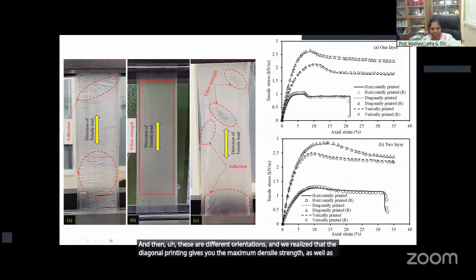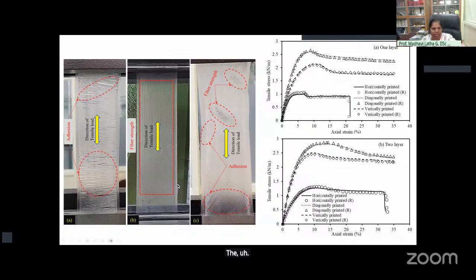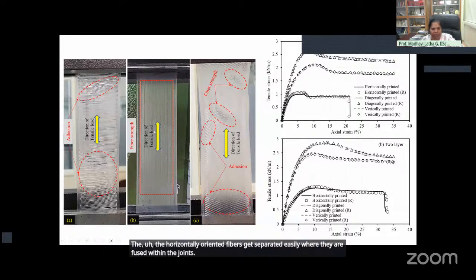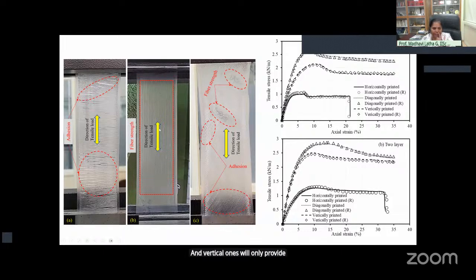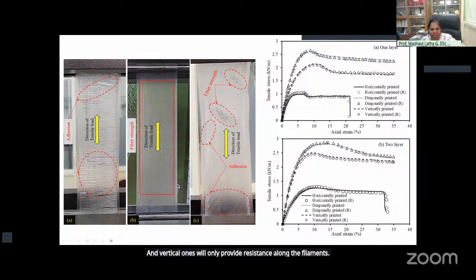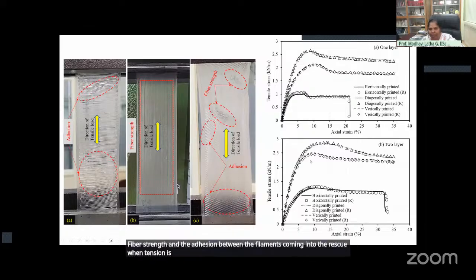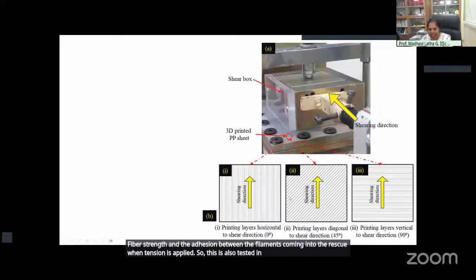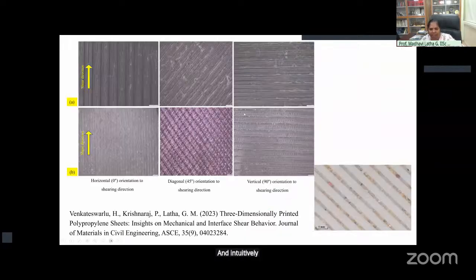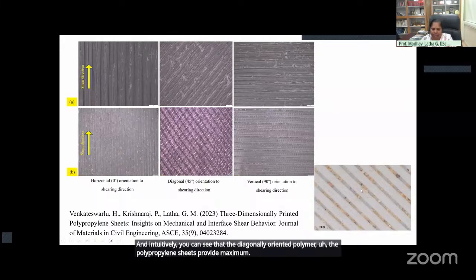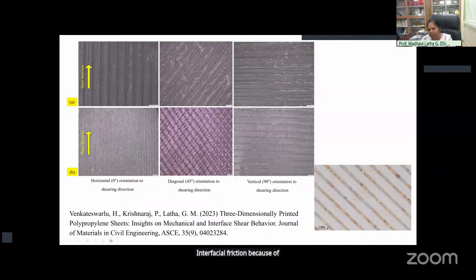well as interfacial friction, because the horizontally oriented fibers get separated easily where they are fused within the joints, and vertical ones will only provide resistance along the filaments, whereas diagonal ones have both fiber strength and the adhesion between the filaments coming to the rescue when tension is applied. This is also tested in interfacial friction, and intuitively you can see that the diagonally oriented polypropylene sheets provide maximum interfacial friction because of higher resistance offered to the motion of particles in the direction of shear.